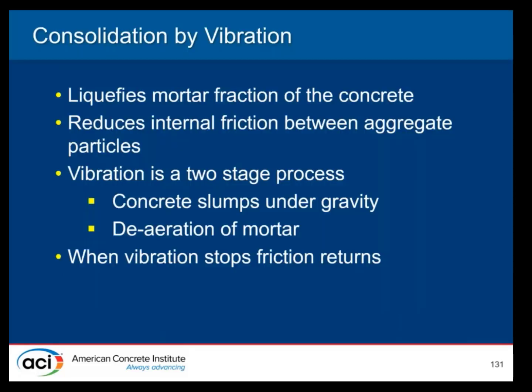Concrete, as we know, when it's placed, is consolidated using what we call concrete vibrators, or vibration. The vibrators basically liquefy the mortar fraction of the concrete to allow it to flow, and drop the internal friction between the aggregate particles. It's a two-stage process. When you vibrate the concrete, it will slump down and flow, and then there's the deaeration of the mortar. When you stop vibrating it, the friction between those aggregate particles comes back.